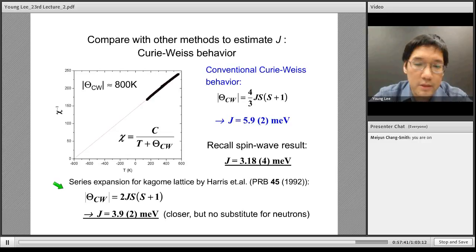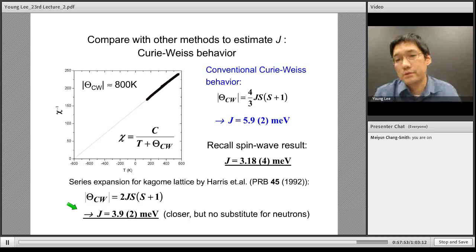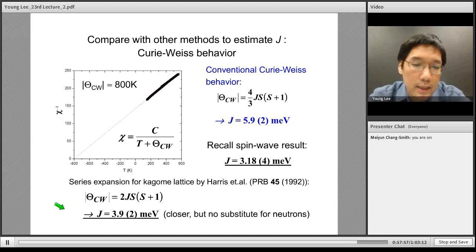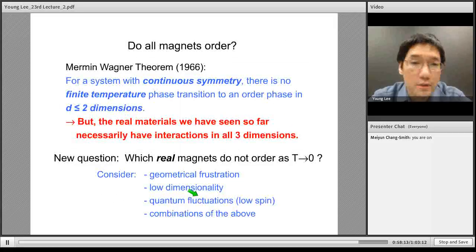And some series expansion calculations show that there are some corrections to the Curie-Weiss behavior, and if you just take the uniform susceptibility data, you get a J now that's 3.9. This is closer to the neutron result. Again, the neutron result is the correct result. It's the best we could measure. So this Curie-Weiss behavior is closer, if you apply the corrections that are lattice specific in this case. But again, there's no substitute for neutron scattering, which is the best way to understand the interactions in magnetic systems.